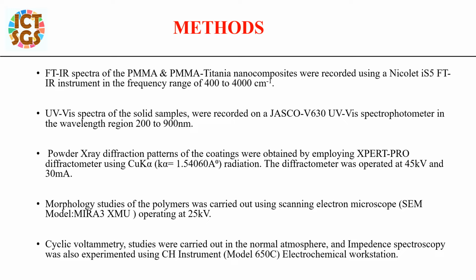Methods: FTIR spectra of PMMA and PMMA-Titania nanocomposites were recorded using a Nicolet iS5 FTIR instrument in the frequency range of 400 to 4000 per centimeter. UV visible spectra of the solid sample were recorded on a JASCO V630 UV visible spectrometer in the wavelength region 200 to 900 nanometer. Powder X-ray diffraction patterns of the coating were obtained by employing an X'Pert Pro diffractometer using CuK alpha radiation. The diffractometer was operated at 45 kV and 30 milliampere. Morphology studies of the polymer were carried out using a scanning electron microscope model MIRA3 XMU operating at 25 kV.